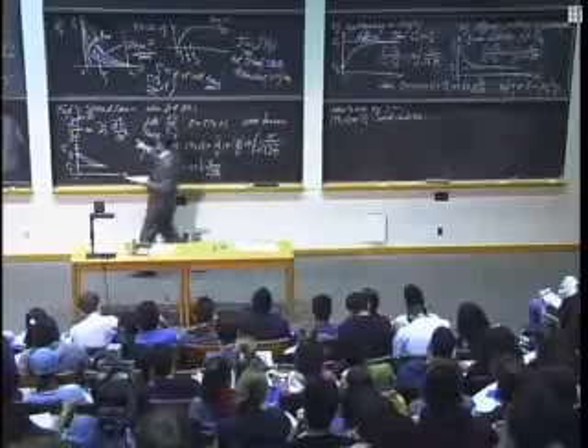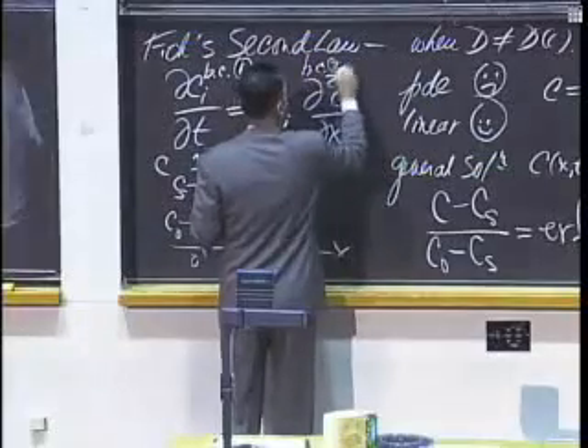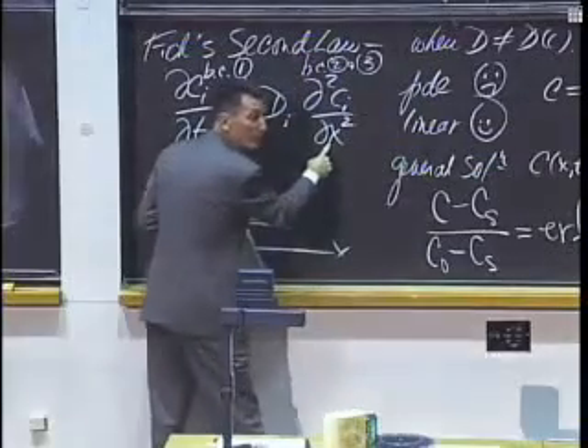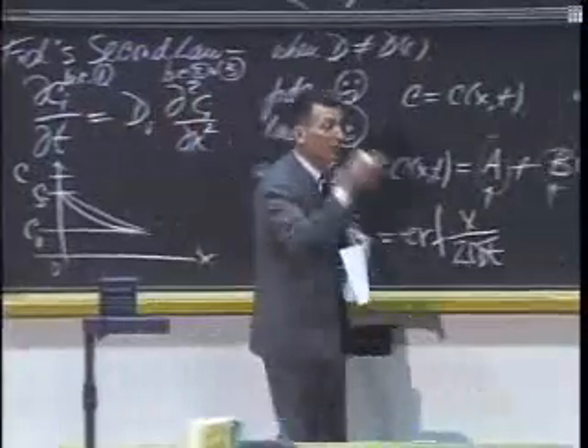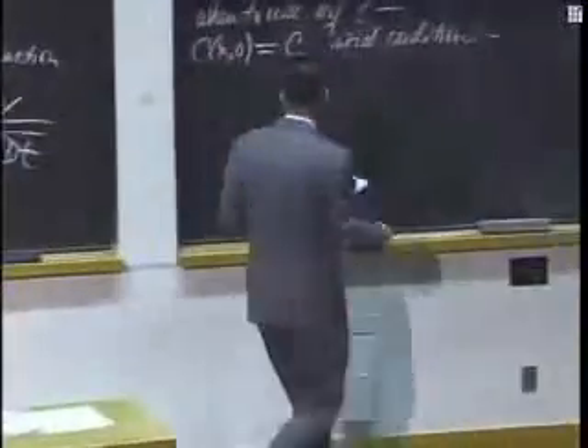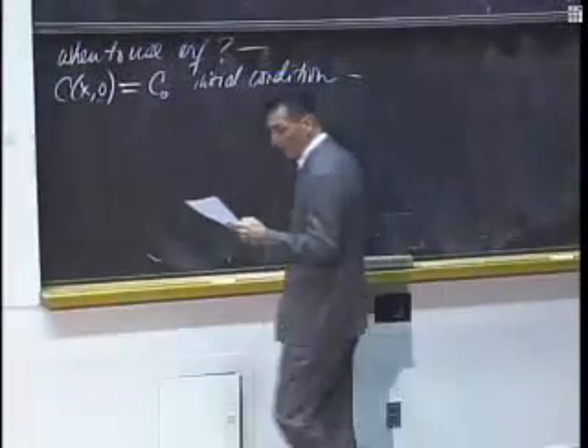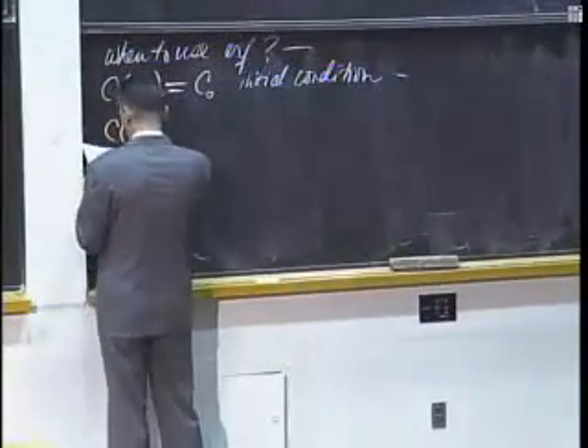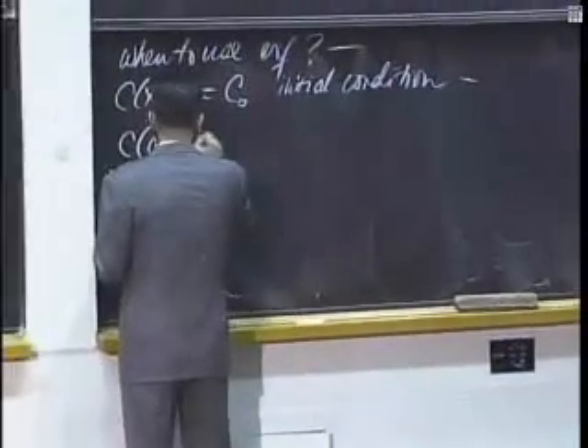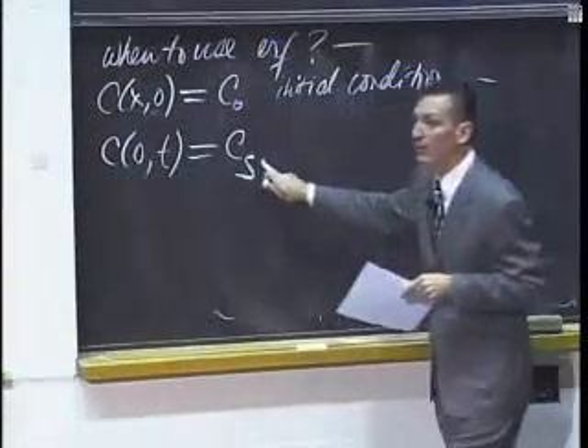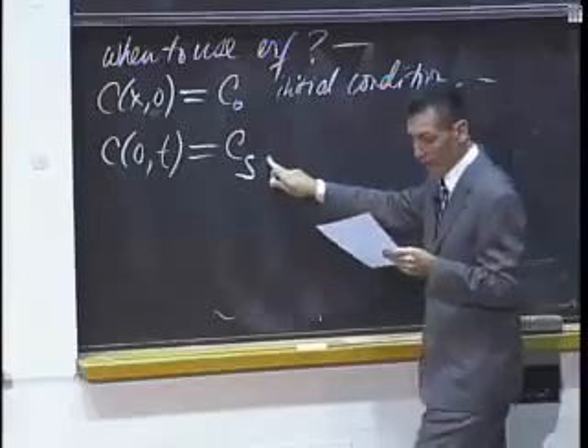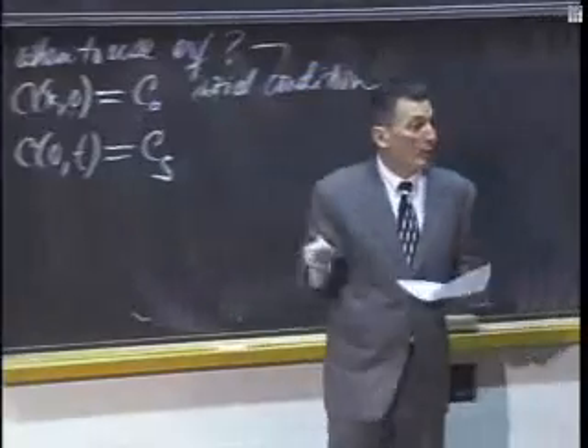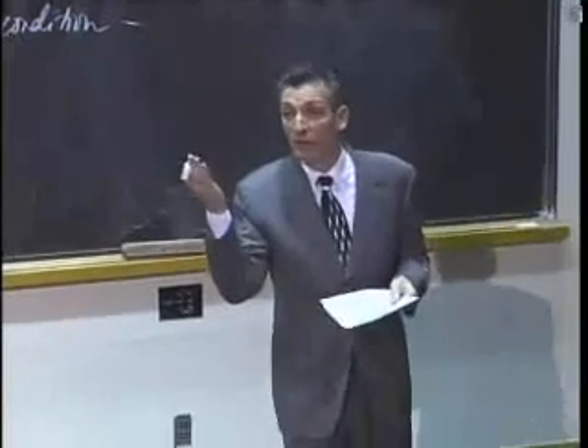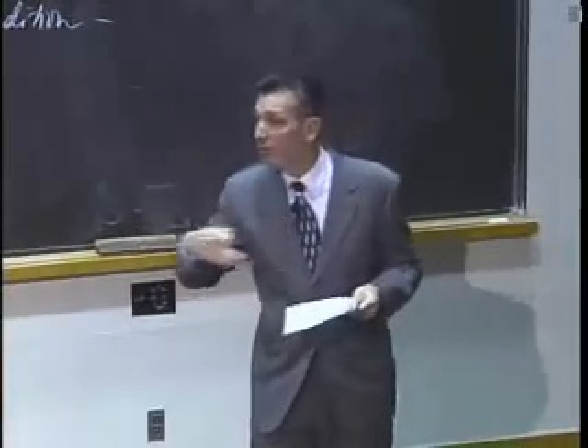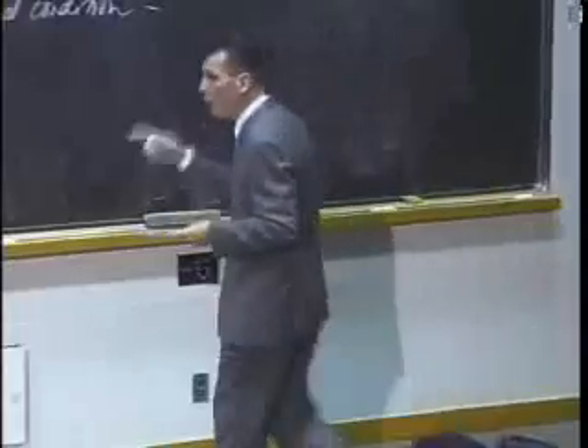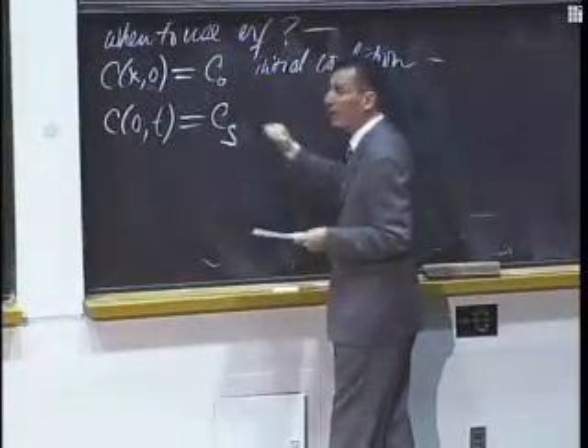Now, we need 2 more boundary conditions. We need boundary conditions 2 and 3 over here, because we got a double derivative, right? You got some function plus constant. When you do d by dx, the constant goes into the trash bin. We need to recover that information somehow. So here's what I've got. I've got C for x equals 0 at all time is a constant. The surface concentration is fixed as a constant, okay? And you say, well, what else could it be? Well, I could have a slowly rising surface concentration, or I could have a surface concentration that varies sinusoidally or something. Those won't work. It must be fixed at a constant value.